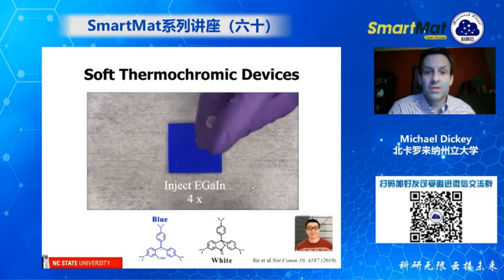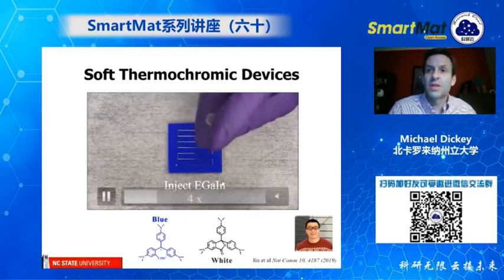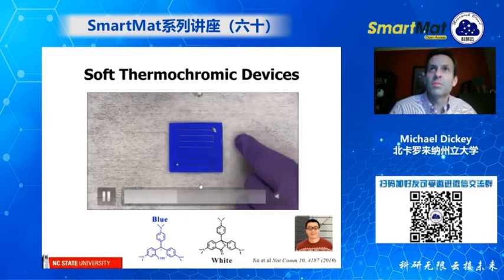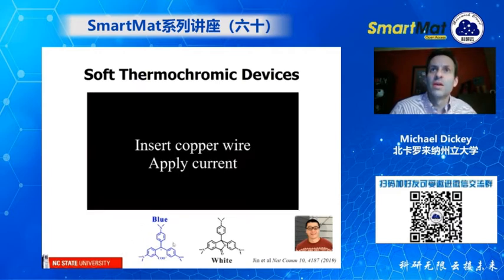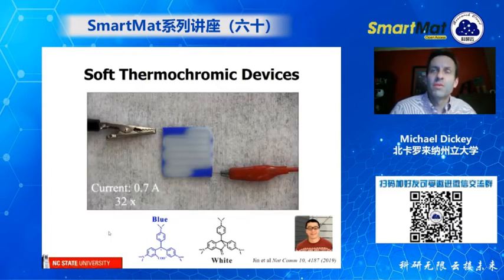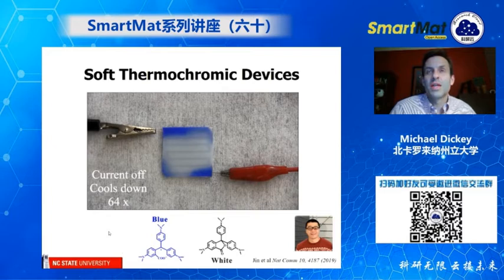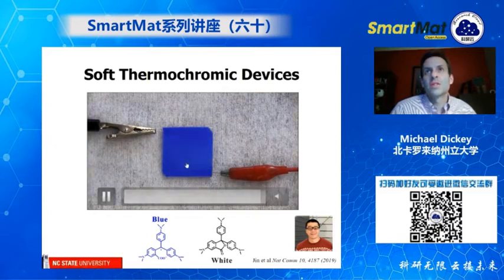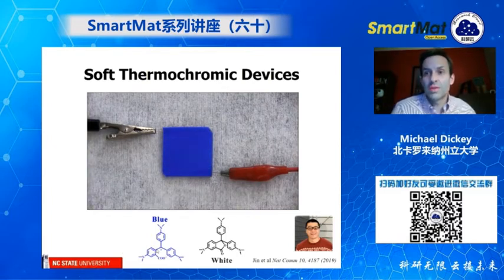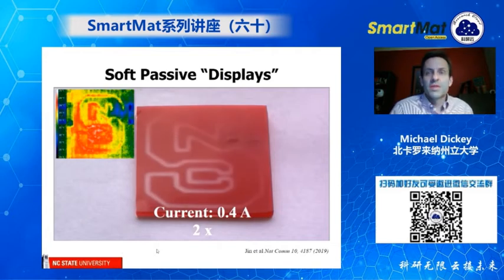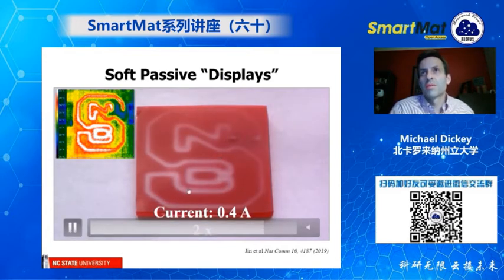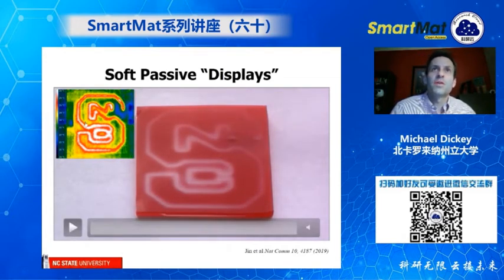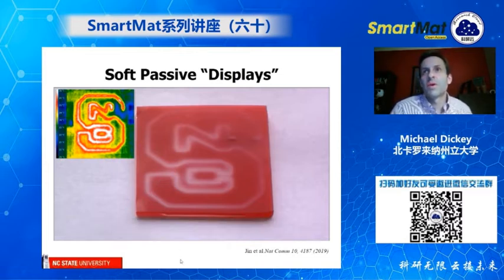And I had a really good Chinese student named Yang who visited us for about a year. And he injected this liquid metal into the silicones that had this blue pigment. Now this pigment, if you warm it up, it will turn white. It actually changes color. And the way that we do this is just by simply running electricity through this polymer. So in this example, we patterned the liquid metal like our NC State logo. You can see the color change of the logo in terms of the thermal imaging, but also in terms of the polymer.